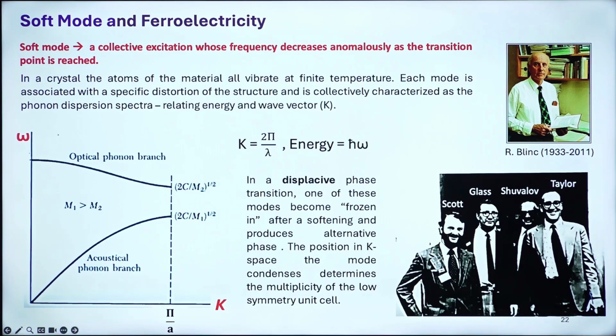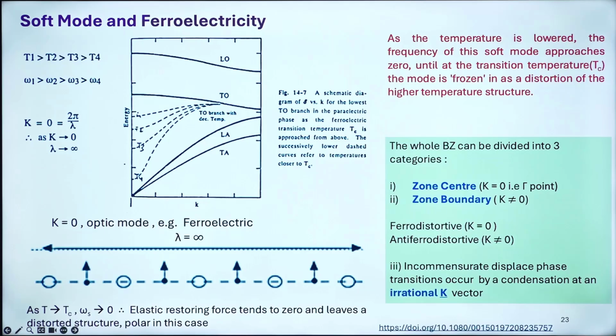It could be infrared or Raman active, both can be identified by using this. So now we will see what the connection is between the soft mode and ferroelectricity. As the temperature is lowered, the frequency of the soft mode approaches 0 until the transition temperature. The mode is frozen in a distortion of the high temperature structure.